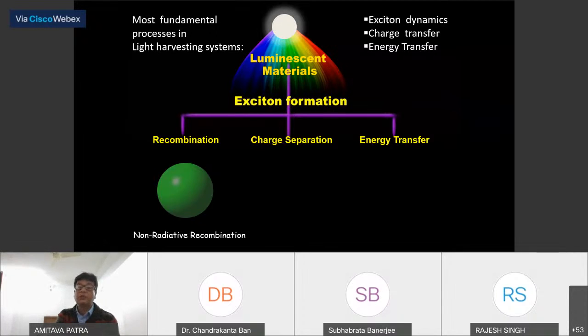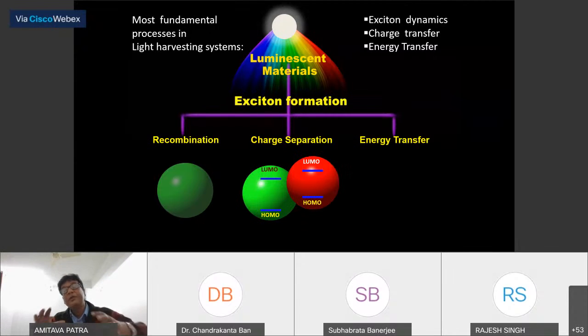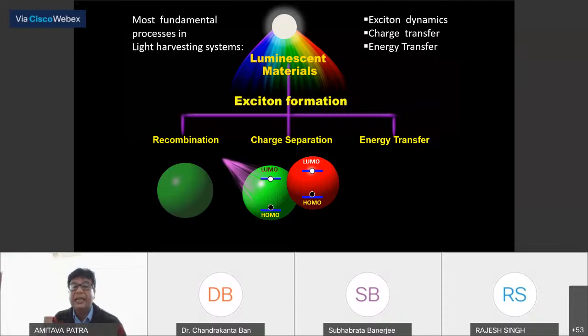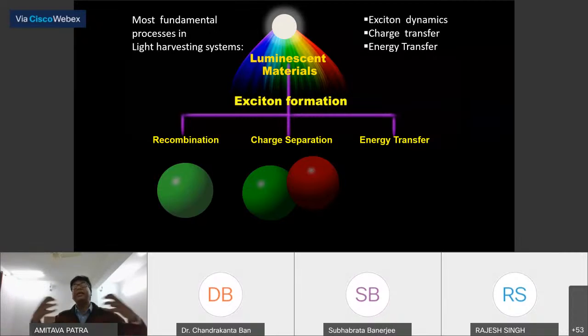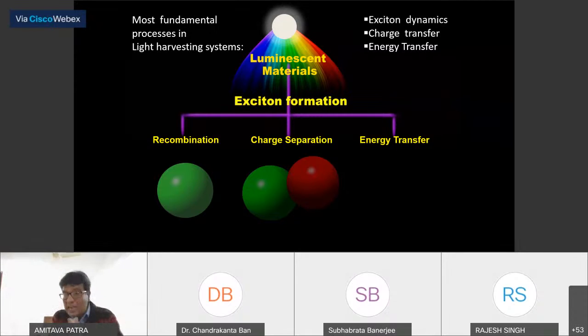The other is the charge transfer process. Why is it important? If you are interested in photovoltaic or solar cell applications or hydrogen generation, then what happens? You have to have a heterostructure, A and B system. Then when you excite by light, electron and hole will be excited, and the electron can be transferred or the hole can be transferred. There is a charge transfer process, or you can extract that electron and hole to generate a photocurrent, right? So the charge transfer process is very important. That whole kinetics is very important.